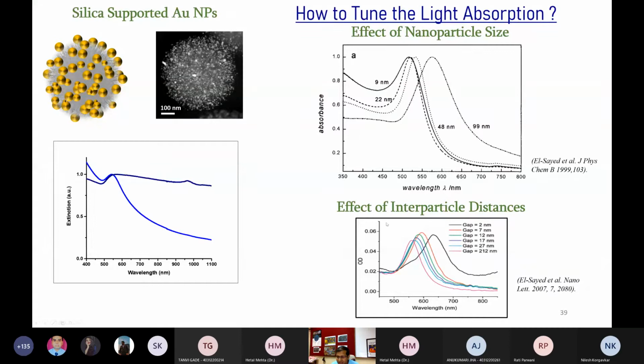Then there is another concept called interparticle distance tuning, where I bring the gold nanoparticles closer and closer, right? And it's more like a pi conjugation in your aromatic ring, where these pi electrons form the ring, and the light absorption can happen at an even lower energy. Exactly the same thing, where when you bring the gold nanoparticles closer and closer, the electron clouds on the gold nanoparticles start to interact with each other, called plasmonic coupling, which allows you to then absorb broadband light.